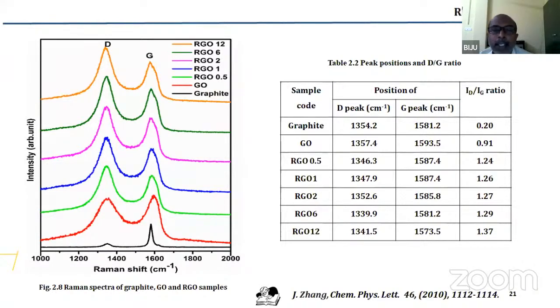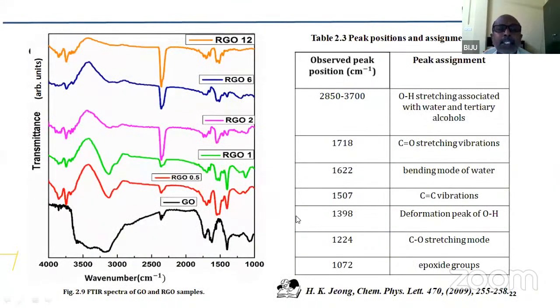And we also found that when we reduce graphene oxide chemically using hydrazine hydrate, the ID by IG value gradually increases. In fact, ID by IG value is a measure of the presence of defects in RGO, and naturally when we reduce, there is some breaking that happens in the layers, some pores are generated, and that is what leads to the higher defect concentration in these samples. IR results were also done, which also supported the reduction due to hydrazine hydrate.